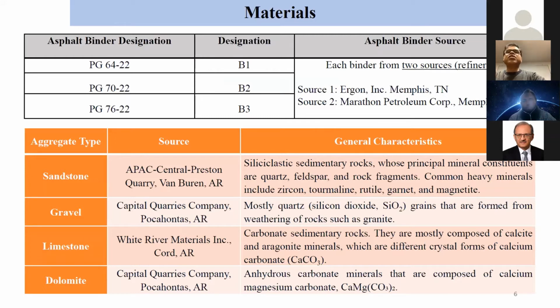All right, so the materials that we used: three performance-graded binders, PG 64-22, 70-22, and 76-22. Those are used in Arkansas and approved by the Arkansas DOT. We designated them binders B1, B2, and B3. We tested all three binders from two different sources, one from Ergon and another from Marathon. Typically, Ergon uses a Canadian crude, and Marathon mostly uses Arabian crude. We were looking to see if crude source has any influence, and actually it does, from other studies we found, but at least we tried two different sources.